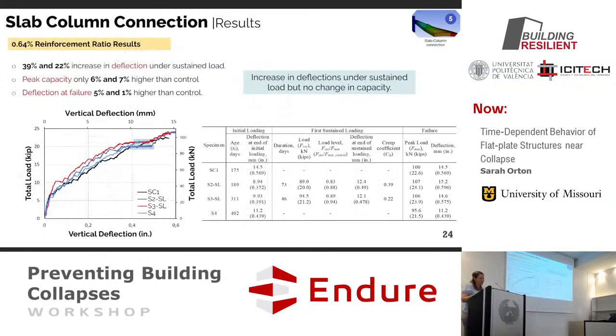So these are some of the tests. These are the ones at a 0.64 reinforcement ratio. So nice behavior here. This black one was the control test, and the blue and red ones are the sustained loading tests. And it's really hard to tell the difference. I have some boxes in here where it's under sustained load. There's definitely increases in deflection under sustained load. But when we loaded it, behavior is pretty much matching the control test. Not really an increase in capacity, really no change in the deflection at failure for this lower reinforcement ratio.